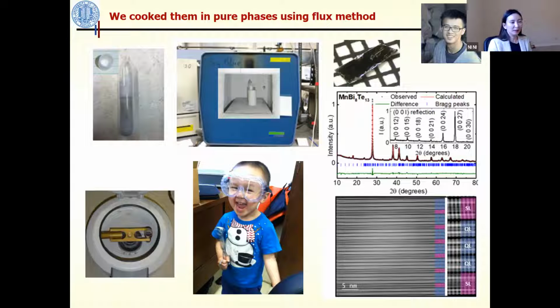It turns out this is a very challenging synthesis project. I have a very good graduate student, Chawi. He found that the growth window for these metastable phases is within several degrees, around 590 degrees. For 147, the growth window is around 2 or 3 Kelvin, and for 1813, the growth window is even below 1 Kelvin. So he has to do a lot of trial and error synthesis to find the sweetest spot in the furnace, so that he can get 147, 1610, 1813.